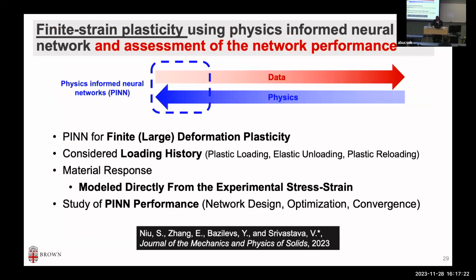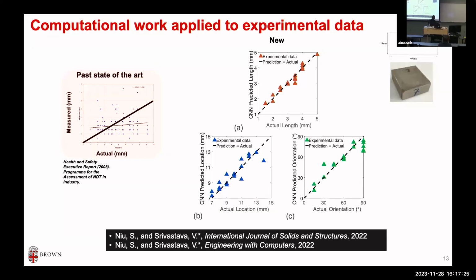How do you make the embedded cracks? Yeah, good question. The problem is making embedded cracks here. Thank God, at that point the 3D printing of metal was established quite well. So these are 3D printed, because there's no way to machine something inside, especially an elliptical 3D crack. Each of these samples at the time cost me $800, so we could only do 25 of them. But these are 3D printed metal samples out of steel. Without that, I was not sure how to work it.